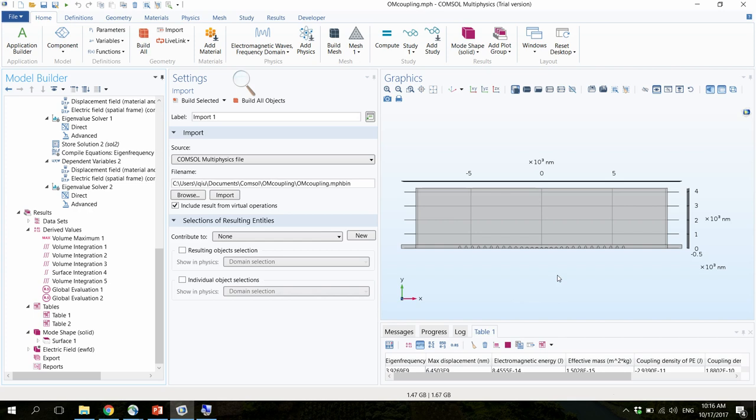I think, as I mentioned, the optimization of an optomechanical cavity is not so trivial, because you need a full band gap for optics and a full band gap for mechanics, while at the same time you need to introduce, as you say, a perfect tapering or geometry change, where you introduce a defect such that you can still have a very good optomechanical coupling rate, which is not trivial. So it turned out that the optimal design, for at least more than 5 years now, is still the original design from Oskar Painter, for silicon at least. And the photoelastic contribution and the moving boundary contribution are actually of different sign.